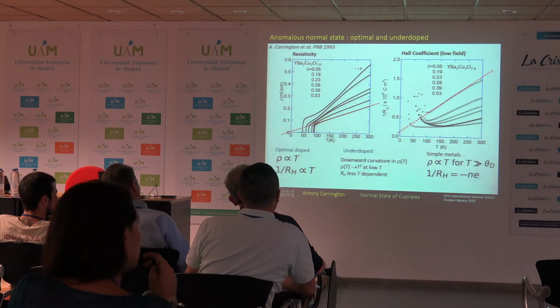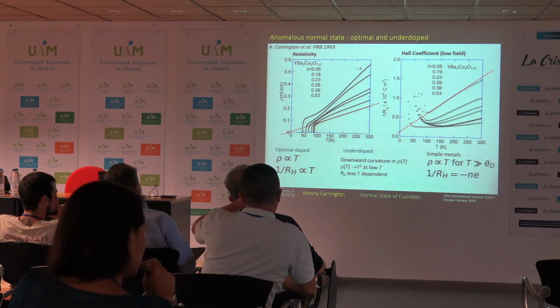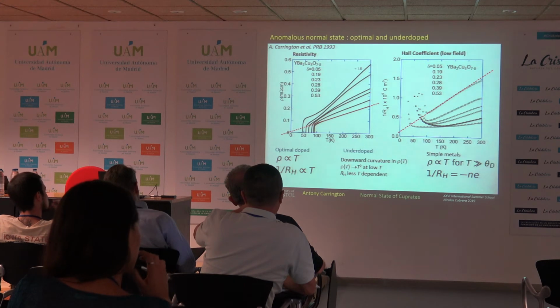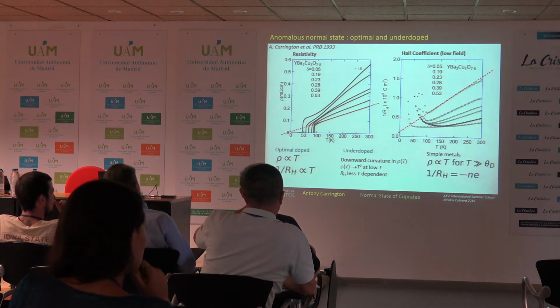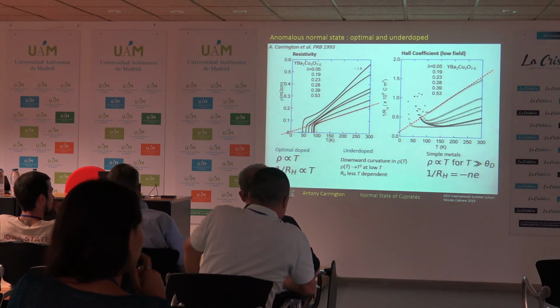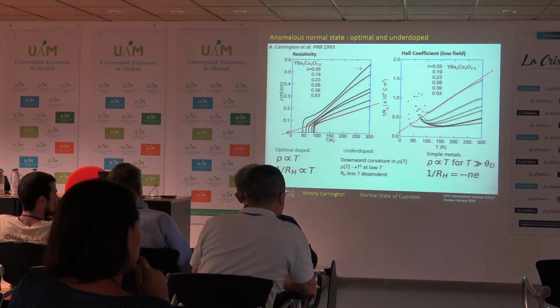The Hall coefficient is also odd. As you know, in a simple metal, 1 over the Hall coefficient should just give you the carrier density. So in a normal metal, you'd expect the Hall coefficient to vary very little with temperature, basically because the carrier density isn't changing.